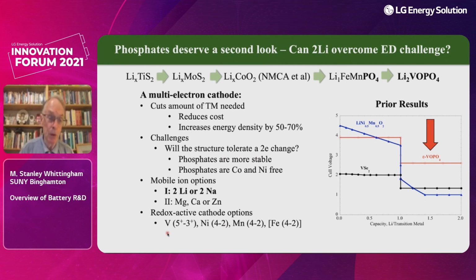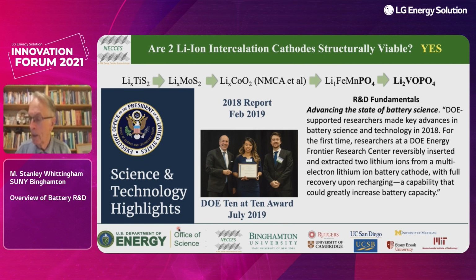The cations we could look at are vanadium, nickel, manganese, and iron. Iron is at too high a voltage for electrolytes. We know these two have not worked so far, so all our emphasis has been on this material. I wouldn't be talking about this unless it did work.